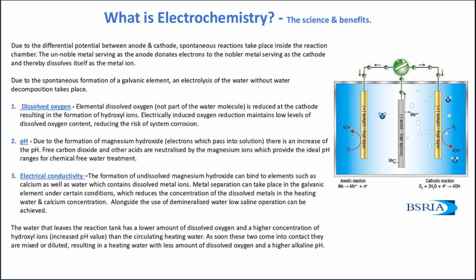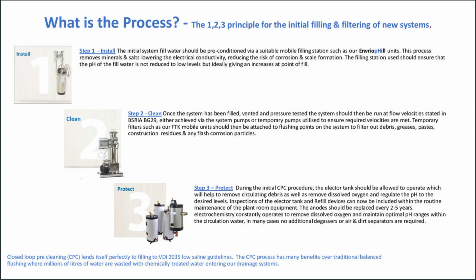The water that leaves the reaction tank has a lower amount of dissolved oxygen and a higher concentration of hydroxy ions, so we increase the pH value, than the circulating water. As soon as these two come into contact, they are mixed or diluted, resulting in a heating water with less dissolved oxygen and higher alkaline pH.